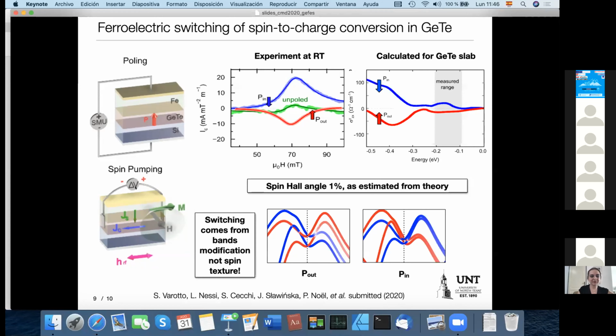just the sketch is a bit different because this sketch should illustrate the spin pumping experiment. So here we can inject the spin current into germanium telluride and, by spin to charge conversion, generate an electric current which is in plane, so perpendicular to the spin current. What is most relevant here is that when we change the ferroelectric state, we can reverse the sign of spin to charge conversion. This is very fundamental and useful for applications. It also agrees well with experimental results, but I may say that not only were the experiments extremely complex, the calculations here were also quite tricky because in principle you cannot obtain this picture while using periodic boundary conditions.